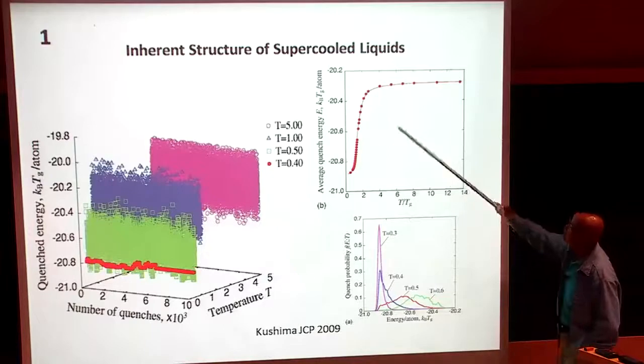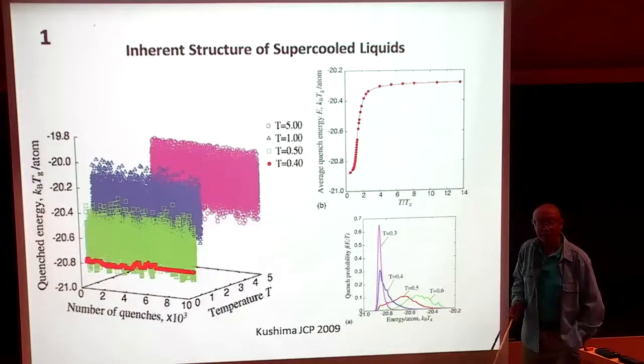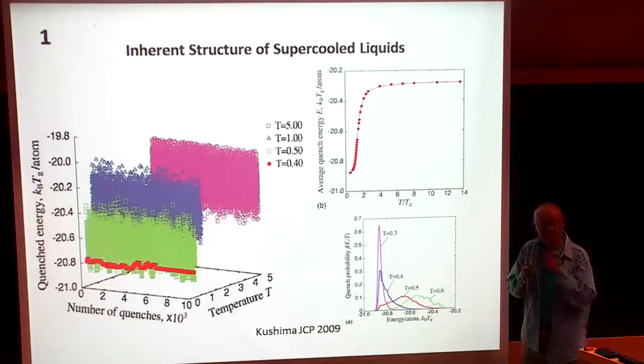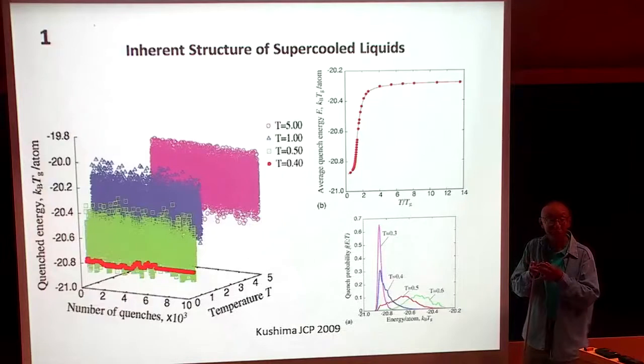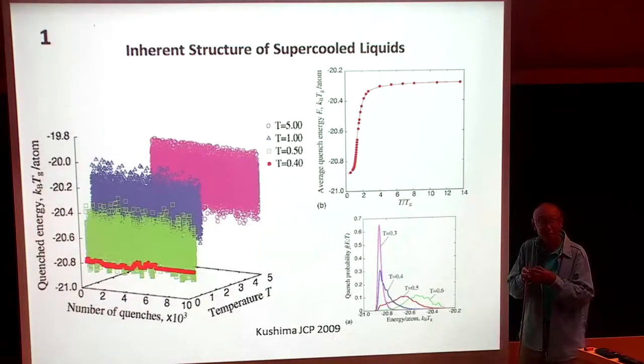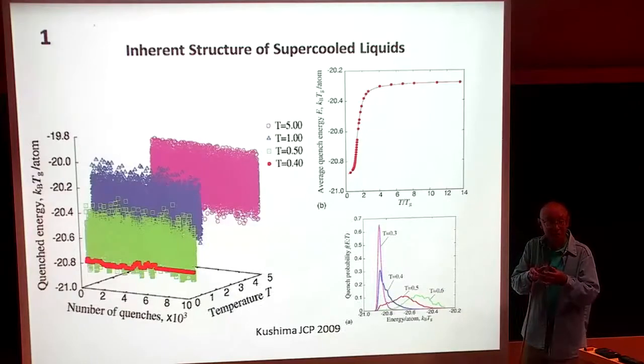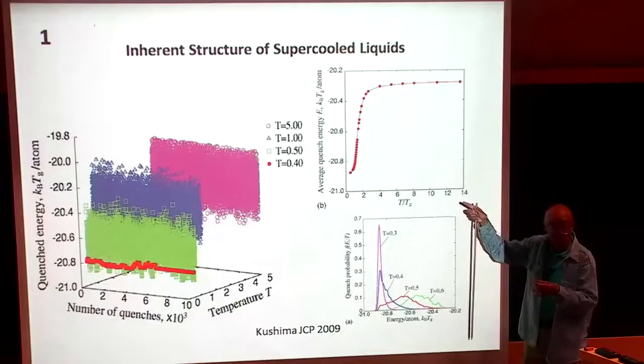So this tells you something. If you think of the viscosity calculation as an experiment, as in any experimental protocol, you have to prepare your sample. What kind of glass? You're going to measure the viscosity of the glass, and the glass depends on what temperature you make it. So you have to prepare a sample. So this is about sample preparation.